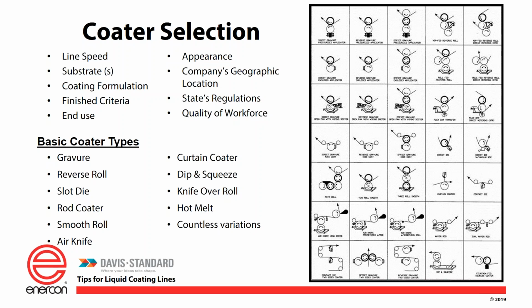An air knife coater, again, that's an excess coater where you're going to put on more coating than what's needed, but then meter it off with an air knife, which will blow the coating off in a uniform fashion. This air knife and the curtain coater I'm going to talk about next actually give you a very uniform coating layer on a substrate. So if I've got valleys, if it's not a flat substrate, peaks and valleys, at the peak and in the bottom of the valley, I'll have the same coating thickness, where these other coaters I just mentioned will give you a flat coating. So it'll fill in the valleys. It won't be as thick on top of the peaks.